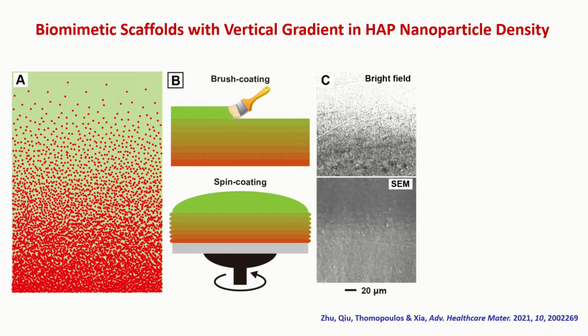And you mix them with a polymer like PLGA, PCL, this kind of polymer. And by using some tricks, you can control the density of these nanoparticles. So eventually, they can form almost a linear gradient along this direction. And now we are exploring two different approaches to achieve this kind of gradient. One of them is just a brush coating. Okay, you can take the solution of this hydroxyapatite polymer mixture, and you coat it, just like we can use even a nail brush.